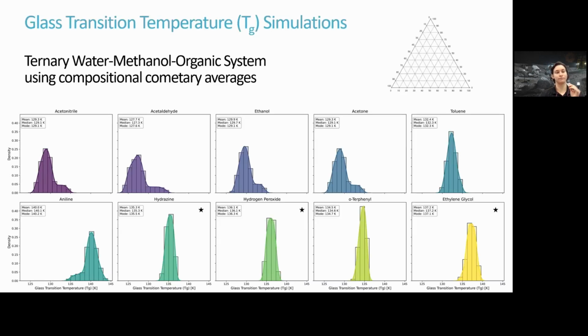Next slide, please. So to begin evaluating more relevant cometary and lunar compositions, I looked at the ternary system first for water, methanol, and then some organic, and you can see the different organic components varied in the histograms below. Now, even at this juncture, we start to see differing organic behavior. You can see some have very narrow distributions, some begin to get more broad and bimodal. Also, the water methanol have a non-ideal correction, but some organic systems behave non-ideally as well, and those had more than one non-ideal correction, which is denoted with the stars. Okay, so how does this all shake out? Next slide, please.